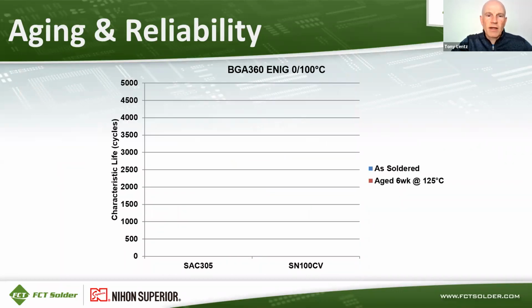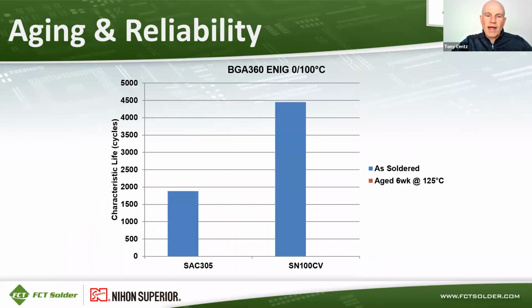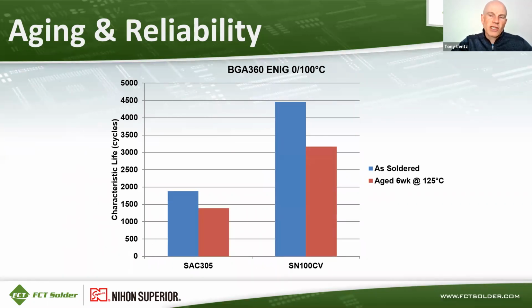Here's aging data for BGA 360 on an ENIG surface finish. The blue bars are as soldered. So SN100CV outperforms SAC305. And then after aging 6 weeks at 125C, again, both of the lifespans dropped a bit after aging, but SAC305 still had a lower life than SN100CV.